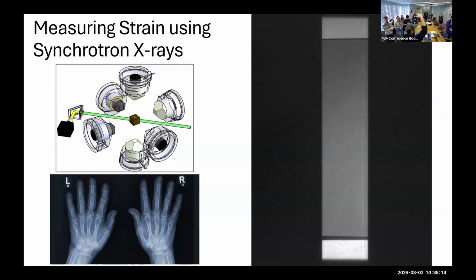So to measure how much strain we have in the sample, so the strain is when a material changes shape. So we have our cylinder, bring it up to high pressure and temperature, and then we push on it harder in one direction, and it's going to strain in that direction. So here, the sample is actually wider than this. So this is the sample. We have our dense Al2O3 pistons on either side of it, and we're going to push it from the top and the bottom, and it's going to get shorter, and we're going to measure that length using the synchrotron.